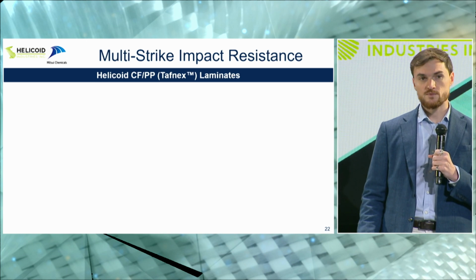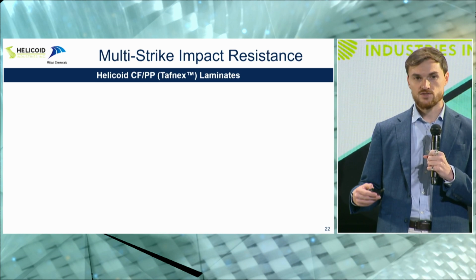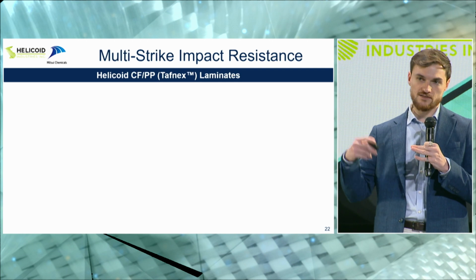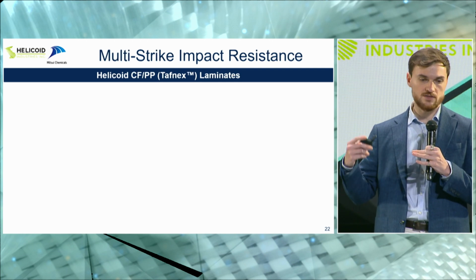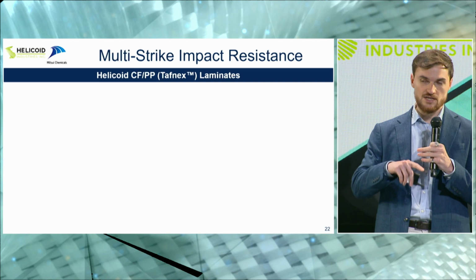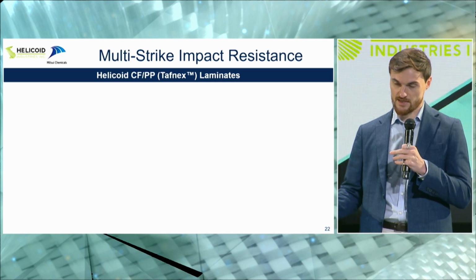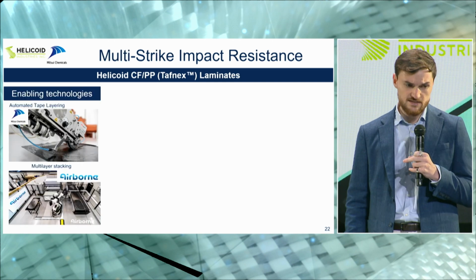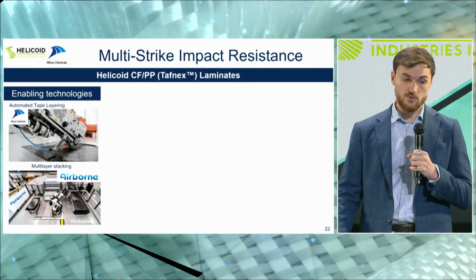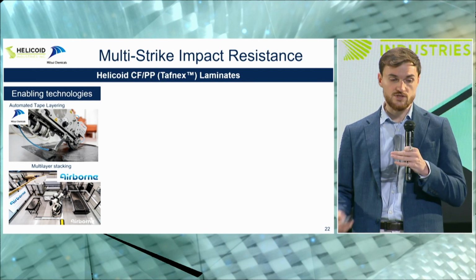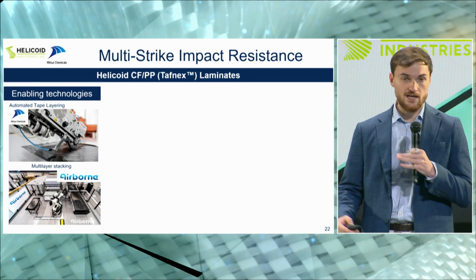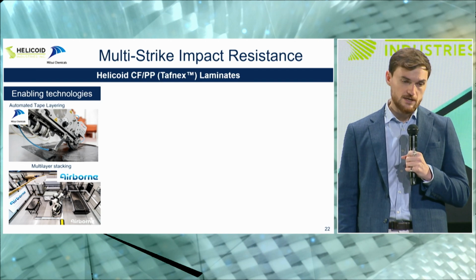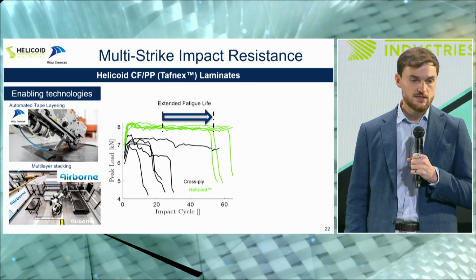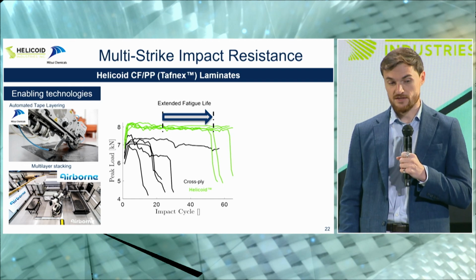And what we performed is multi-strike impact. So you have your sample, you impact it multiple times in the same spot at the same energy level, and you see how the performance degrades over impact cycles. In this case, the manufacturing was enabled also by Airborne through multilayer stacking that allows to deploy our technology in commercial products. And this is the type of results that you obtain from this test.